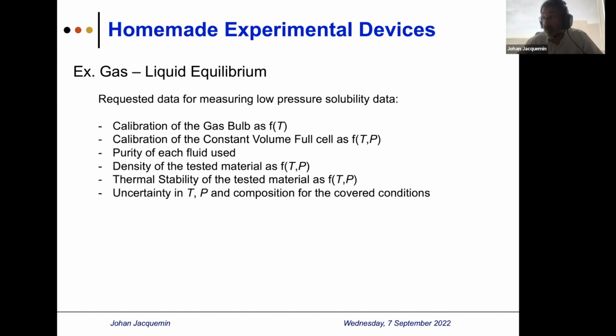And as we discussed previously, how can we determine accurately the uncertainty of solubility? From my point of view, this could be done in different ways. Could be done thanks to the calibration, the repeatability from a reference system, and by measuring the system several times. My recommendation is to do your measurements at least 4 or 5 times, even if each solubility data point could take sometimes 1 week. And we must also take into account calibrations thanks to reference material, like, for example, gas solubility in water, as an example.